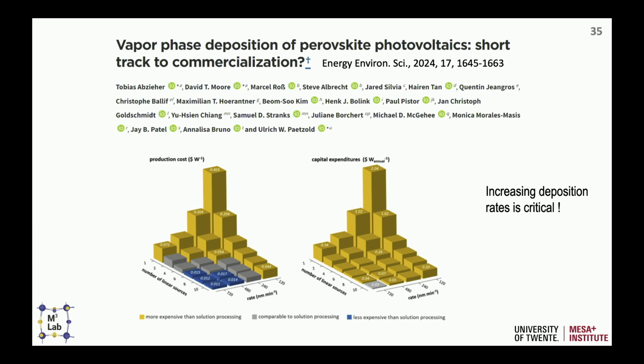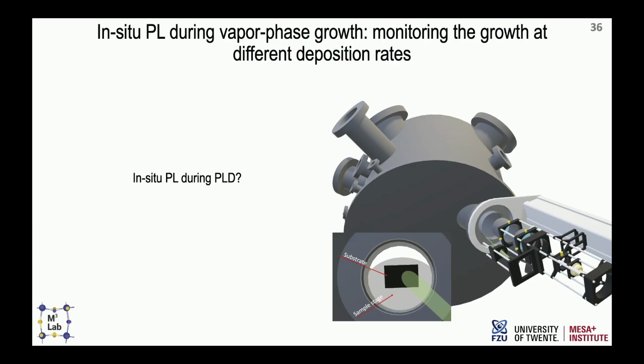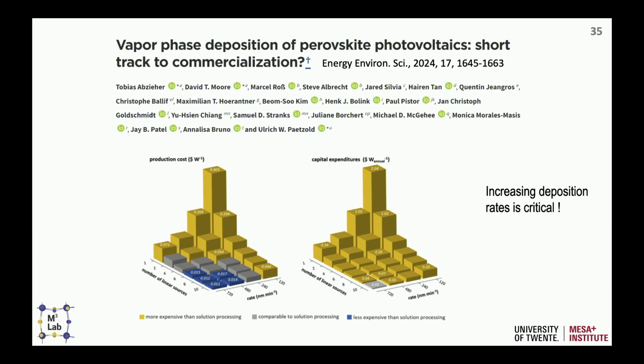And this graph shows the production cost, so dollars per watt. And you see that to get this down to here, which is the lowest possible, you need to increase the number of linear sources, either evaporation sources or laser sources, whatever you want to call it. But also, you need to increase the deposition rate. So this is 120, this is 720. So really, to go for something that is industrially feasible or interesting, you really need to go for high deposition rates. So it's a very important thing to work on. There are some groups in co-evaporation working on that. And in our case, we said, okay, we really need to do it as well. And that's also one of the projects we have in the Solar Lab or Solar NL program.